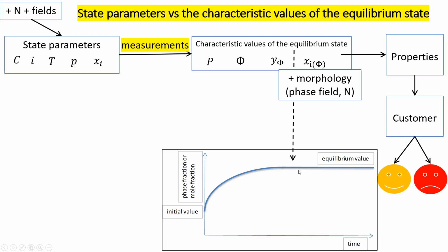Now, how do you know, by the way? Well, you can know only by sampling at different times, and when you see that nothing is changing anymore, and by the way, the same result is obtained from the bottom and from the top, then you can be sure this is the equilibrium value. And then when you have reached the time needed to reach equilibrium, then you cool the whole system very fast.